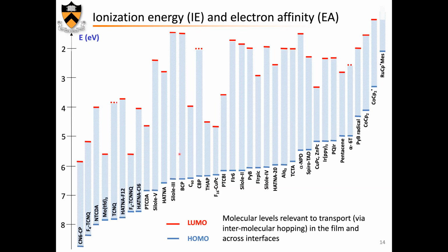So you can see that some of these have huge gaps of 3 or 4 or more electron volts, some of them much smaller. But also you have an enormous range of ionization energies from 8.5 or more electron volts down to 2. And the same thing, of course, for the electron affinity. So some of these molecules will eventually play the role of very good electron donors for n-doping the material, or electron acceptors for p-doping of the material. But I just wanted to show you this slide here, which shows again the enormous flexibility of the material parameters and the material space that we have here.